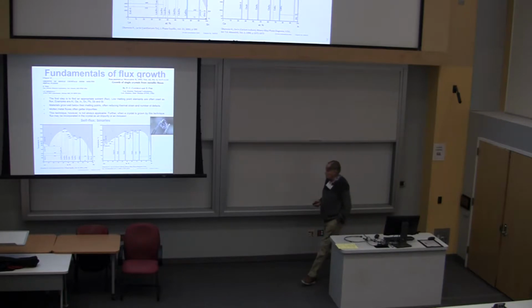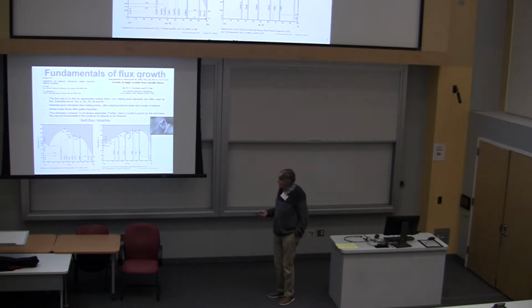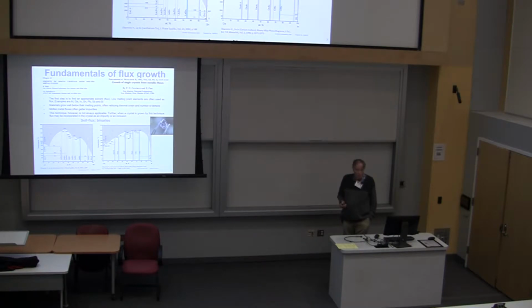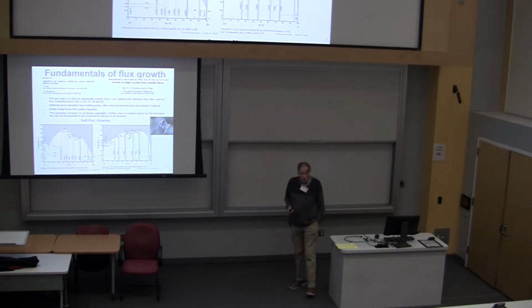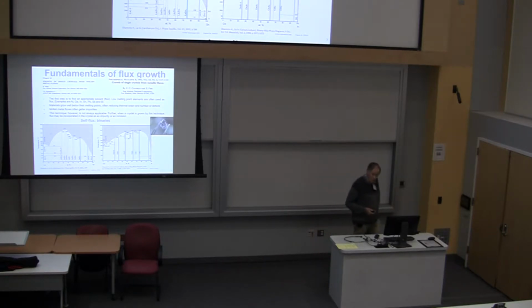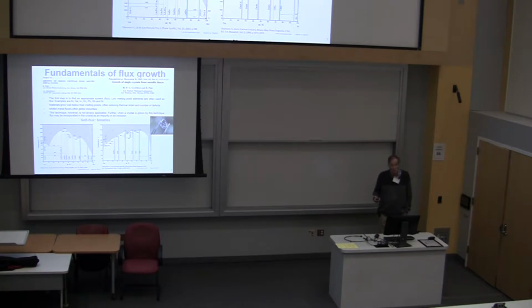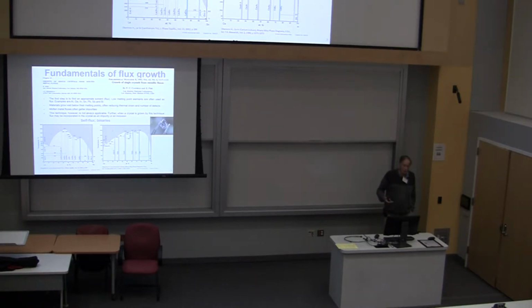You might say that, for instance, with a pure lanthanum melt, if you melt lanthanum in aluminum oxide, it will eat the crucible. Lanthanum oxides are extremely stable. But when it's dissolved in tin, the activity of lanthanum goes way down, and so you get very little crucible attack. Of course, this kind of melt is very reactive in air. Tin is reactive in air. Lanthanum is reactive in air. So you need to have some kind of a cover, meaning an inert atmosphere, for it to be in.